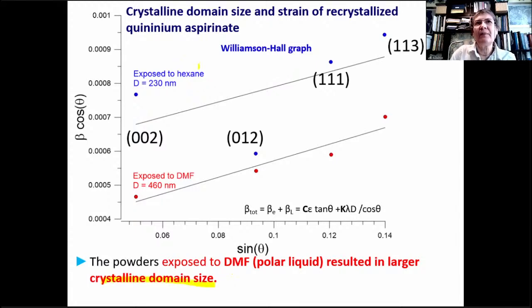And we can see, from the width of the powder diffraction peaks and how that changes with the theta angle in the diffraction data, that the powders exposed to dimethylformamide lead to a larger crystalline domain size than the powders exposed to hexane, which are less crystalline, less well crystallized. So this domain size is smaller. And this could be due, there are many options, but it could be due to the solubility. Like, the material is a salt, so it's probably more soluble in a polar solvent such as dimethylformamide than in hexane. And it could also be related to the dielectric constant of the solvent, which should be higher for dimethylformamide.